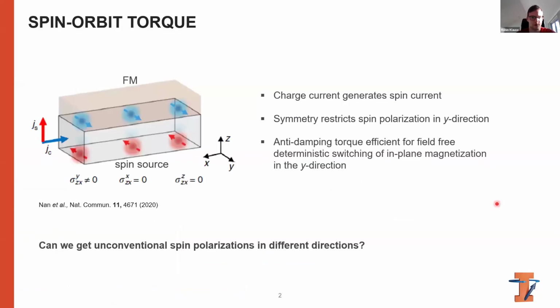To start off, I'll briefly review spin-orbit torques in general. If you have a spin source, typically a heavy metal like platinum or tungsten, and send a charge current through that spin source in the x direction, you generate a spin current in the z direction due to the spin Hall effect. The spin polarization of the spin current is in the y direction, and this direction is restricted by the symmetry of the spin source layer.